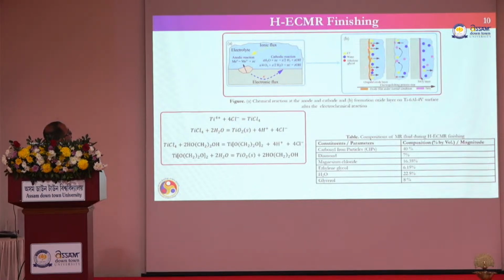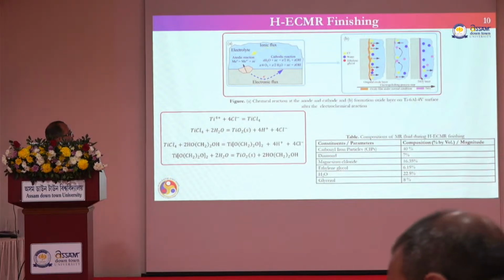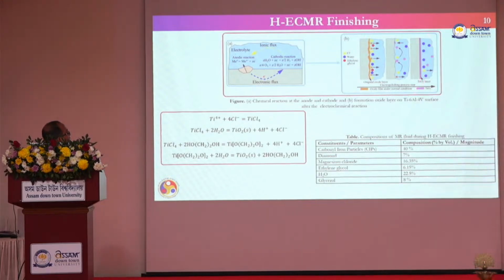Okay, so this initial oxide layer is very thin, and it is not uniform also. After electrochemical machining, you can see that there is a thick layer, around 75 micron thick, of this titanium oxide layer, which is generated because of the chemical reactions with the electrolyte on the titanium alloy.